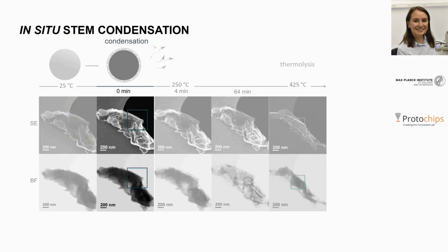Therefore, using these insights from in-situ and ex-situ observations, we performed synthesis of materials in a vacuum oven, which, as expected, led to the formation of particles with a mesoporous surface. The condensation in vacuum occurred also at lower temperatures, and already at 250 degrees led to the formation of hierarchical porosity and 2 times higher CO2 uptake compared to nitrogen samples.